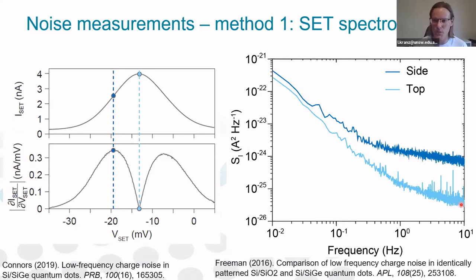Okay, so by doing this comparison of data taken on the side and on the top of the SET peak, we confirm that the fluctuations in tunneling current are dominated by fluctuations in electrochemical potential in this device. So having confirmed that, we go back to the measurements on the side of the SET peak.